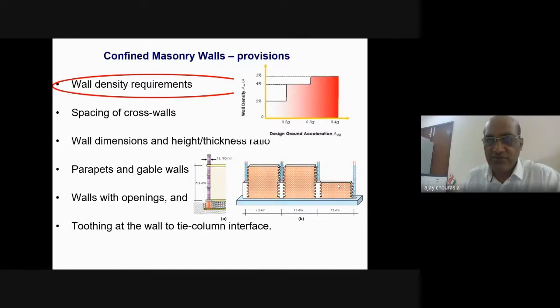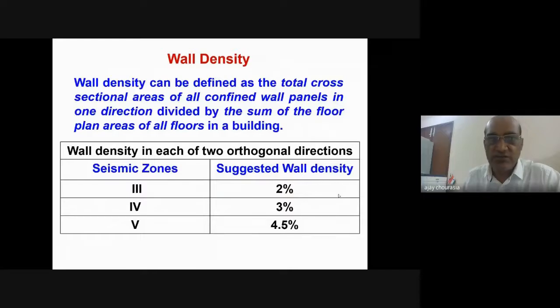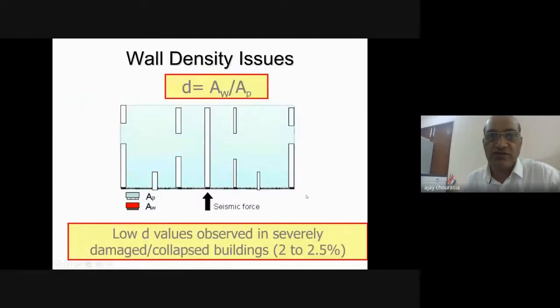Wall density can be defined as the total cross-sectional area of all the confined walls at the sill level, because when you calculate at the sill level, it takes care of the openings in terms of doors and windows, in one direction, divided by the sum of the floor plan area of all the floors in a building. When you calculate this ratio in one particular direction, for seismic zones 3, 4 and 5, it should be in the range of 2, 3 and 4.5%. In short, D is given by AW by AP.